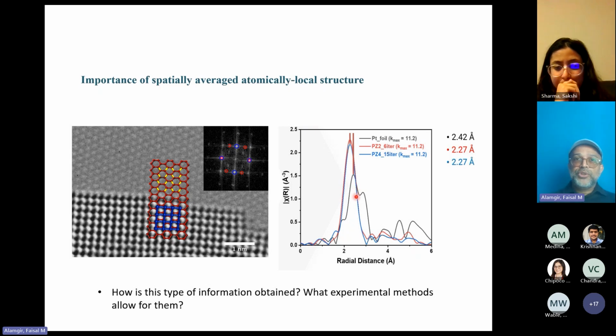So here you do not have to worry about, well, is my information coming from this region of the sample or that region of the sample. It's actually averaged over the entire sample. And on average, we can now say that the platinum atoms are closer to each other by virtue of the fact that they have an epitaxial relationship with the graphene.